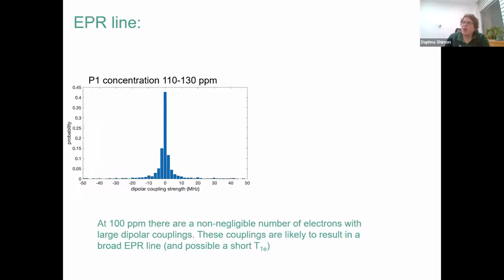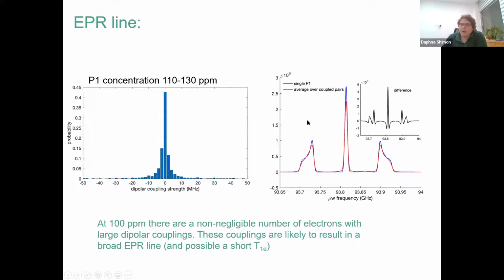And so what we did was we looked at the probabilities for different dipolar interactions to occur at 100 ppm concentration of P1 centers. And so you can see here that there's a pretty wide distribution of dipolar interactions that are probable. But when we simulate the EPR line for a single spin in blue, or for a combination of pairs, each one with a different probability and a different dipolar interaction, we get the red line. You can see in the difference that the effect is mostly symmetric on the edges of each line. And so it's not 100% clear that there would be a fast relaxing electron group that's shifted inwards to give us the DNP enhancement from the truncated cross effect.